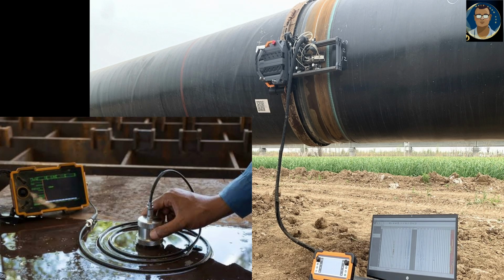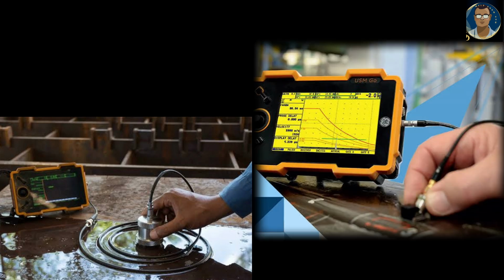A calibration block is also termed a reference block, and there is another block required to demonstrate the specific scanning plan for each and every joint design, which is also called a validation block or mock-up testing block. There are hidden defects which the technician does not know. If the technician can catch all small or bigger defects, then the resolution and the accuracy of the scanning plan is proven through that demonstration. So the procedure of AUT is generally approved by this mock-up test, which also proves that the technician is qualified. So one demonstration gets the procedure as well as the technician approved for AUT.